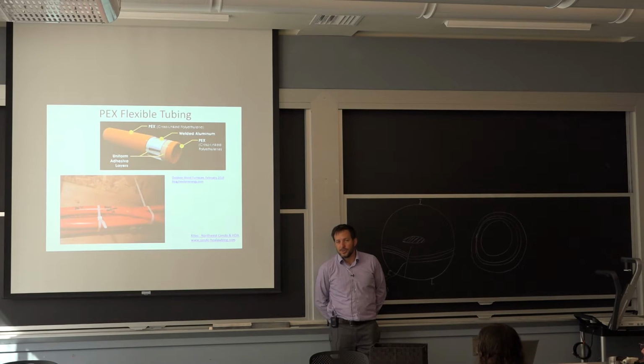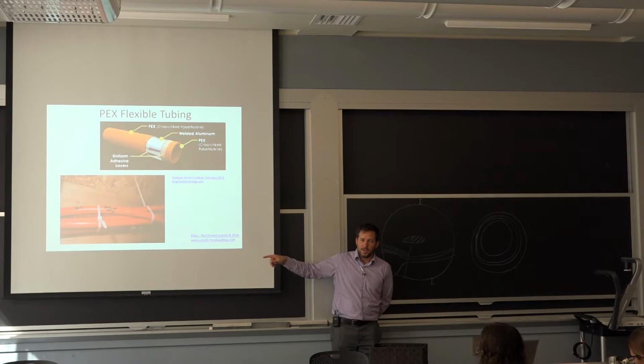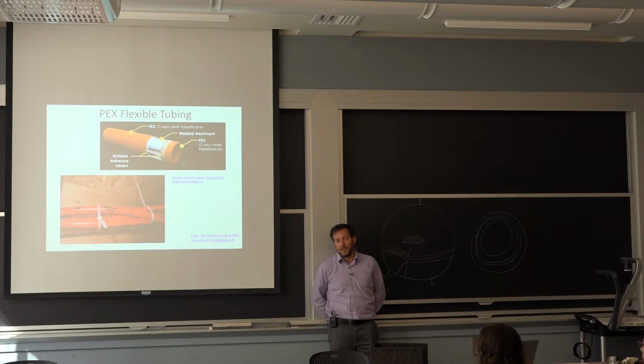The only problem was the people that were making this didn't realize that it was also going to be used in a high oxygenated water environment. So they didn't change their antioxidant package. They used the cheaper antioxidant package. There's a cost associated with that antioxidant package, but by the time they fix it, it's still used. But this is exactly like the CPVC system. It's down the road that they were able to avoid the problem. It was a little bit of a bigger problem with hot water. You get a little bit more oxidation, but it was happening in all the cases. So kind of another lesson learned by mistake.